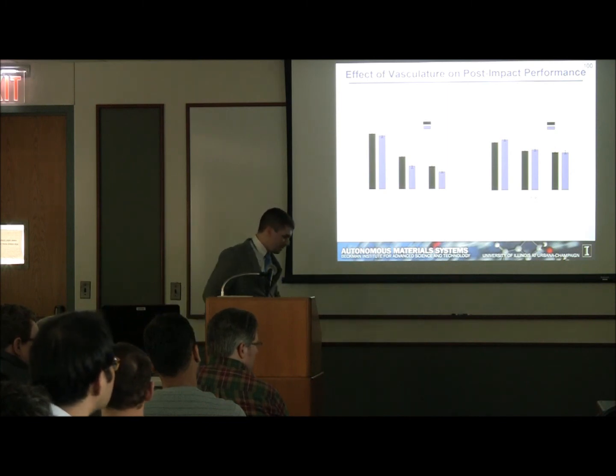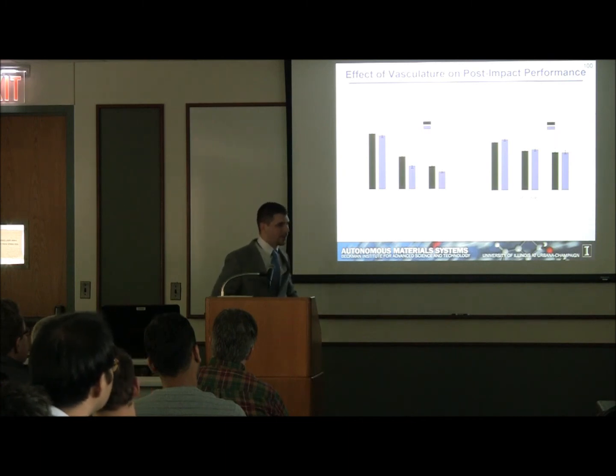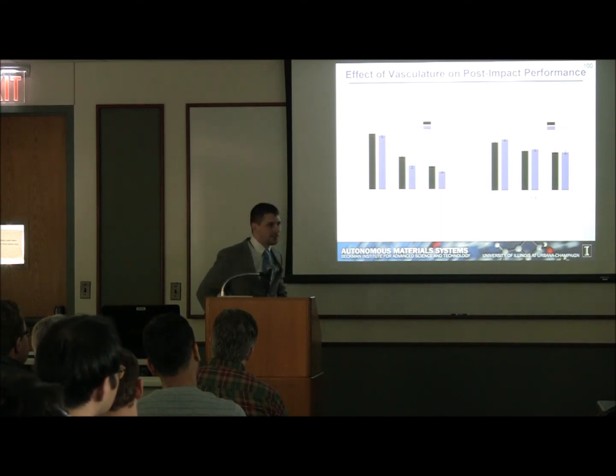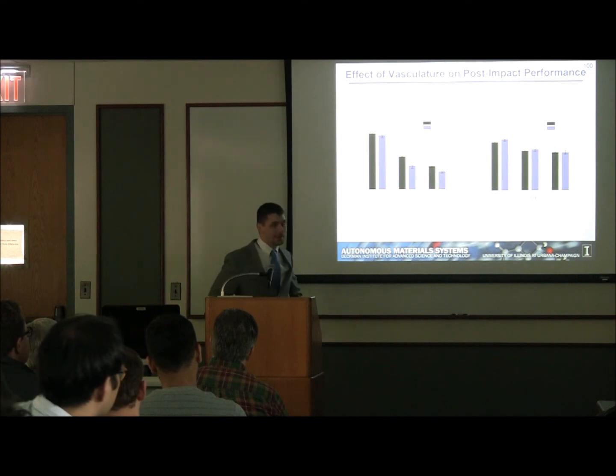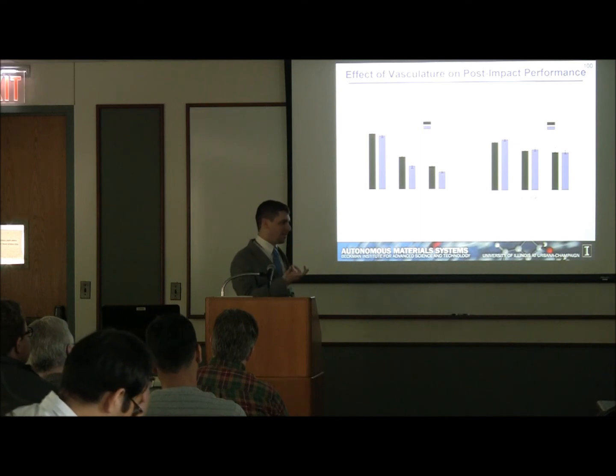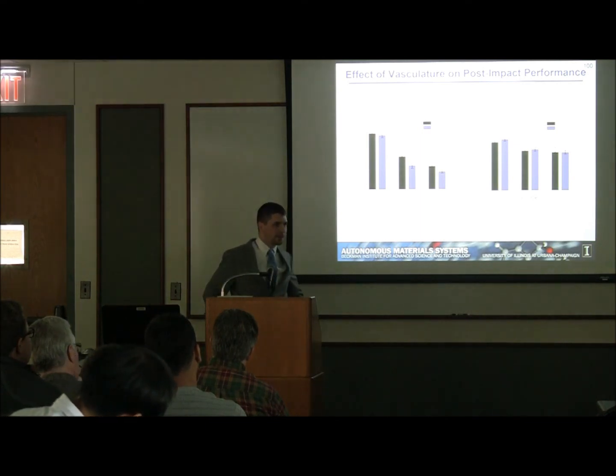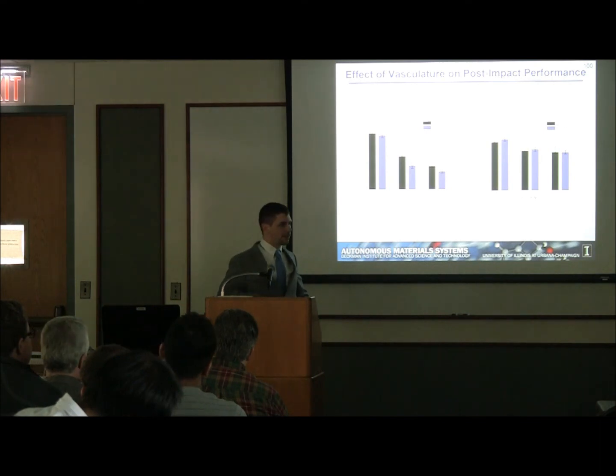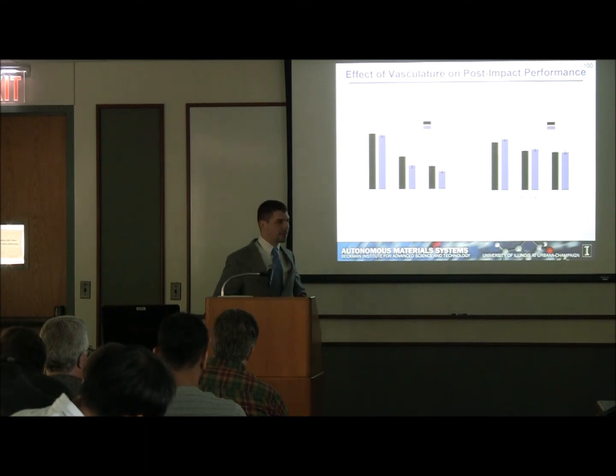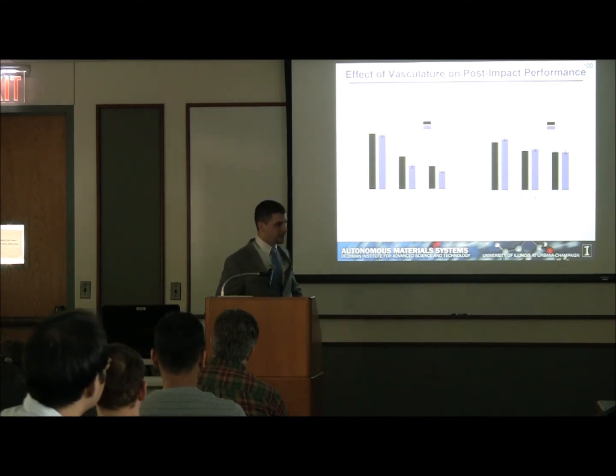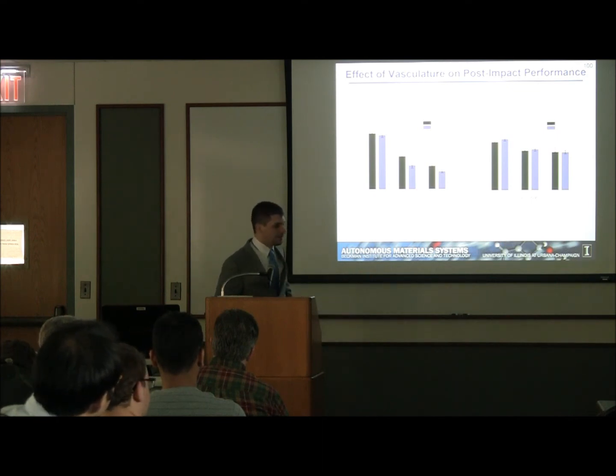Yeah, I have considered it. One particular issue is capsule stability at high temperature. We require 200 degrees Celsius for 24 hours to complete the vascularization process, and the capsules typically don't survive that. A paper was published recently by someone at Urbana-Champaign that looked at adding a different polymer coating, polydopamine, to the outside of the capsule to increase its thermal stability up to 180. Then Amanda Jones capitalized on that in one of her papers. So I think this technology has come along, and it could be viable. Actually, in the conclusion to my dissertation, I make note of that. So, yeah, it's really interesting.